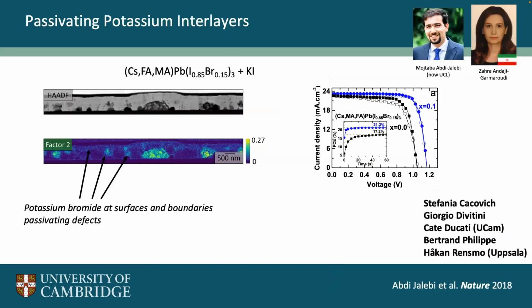We've also been adding in some different additives. So this is an example where we add potassium into the sample, and what we see, this is a cross section of the cell, is that the potassium decorates the grain boundaries, and in fact, these interact with some of these defects and actually passivate those trap states, and we see a good performance increase in the solar cell as well.